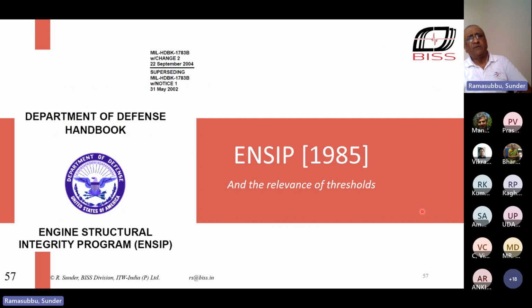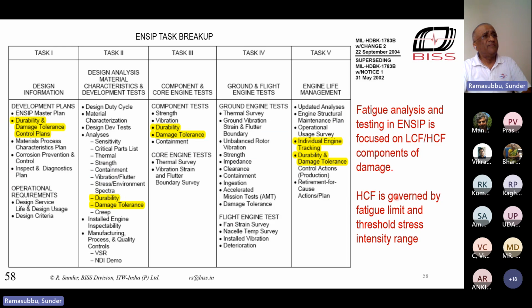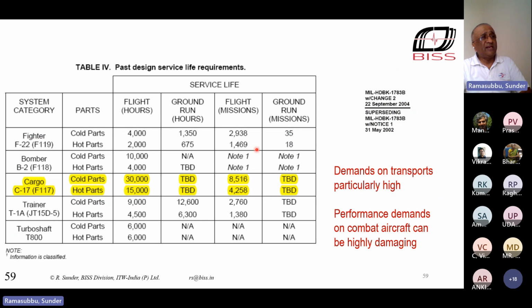Now, briefly about the engine structural integrity program. It has the same structure as the ASIP, but the important difference here is the focus on the low cycle and high cycle fatigue approaches to fatigue life of engines because they are rotaries. They rotate at from a few thousand to a couple of 10,000 RPM. And if there's one load cycle in each of these due to some reason, you have a huge cycle count, unlike an airframe.